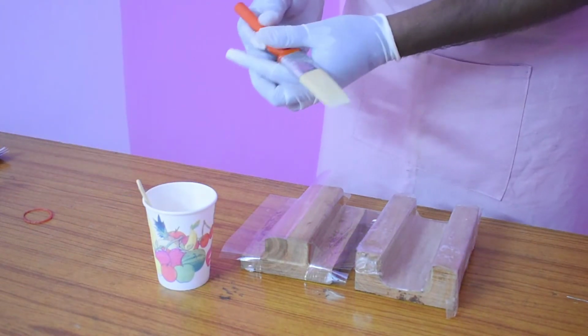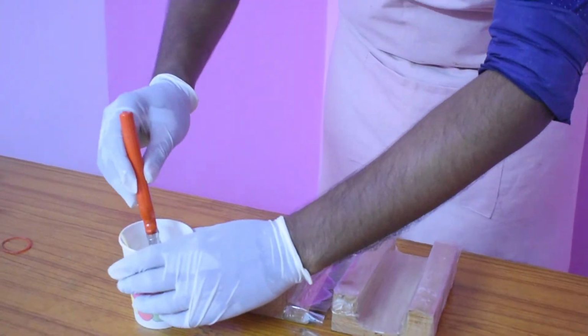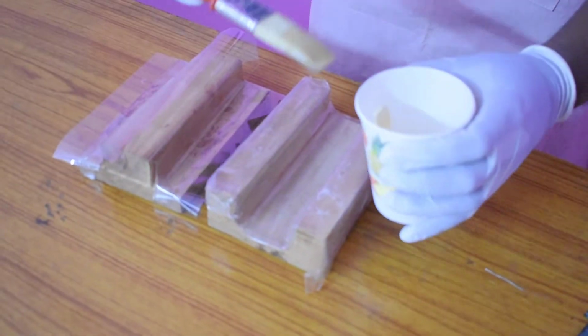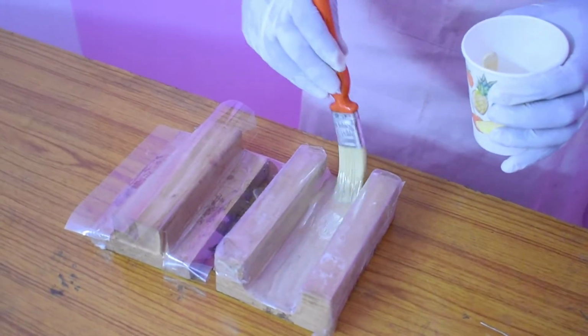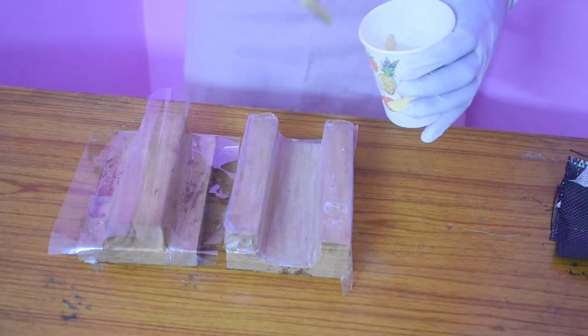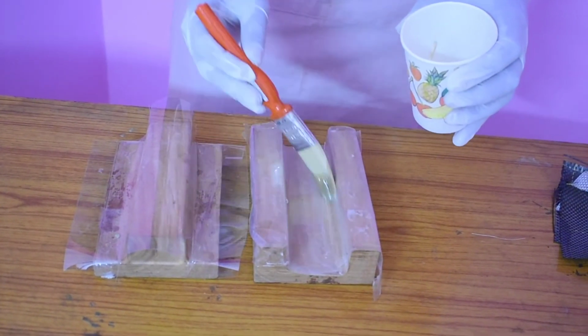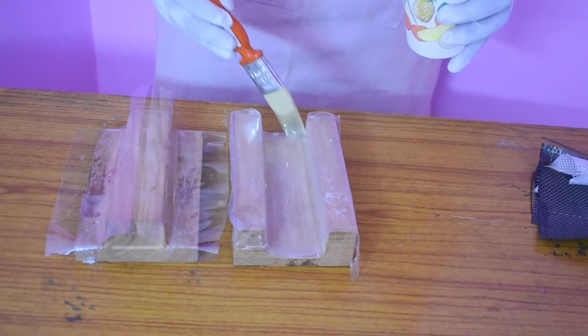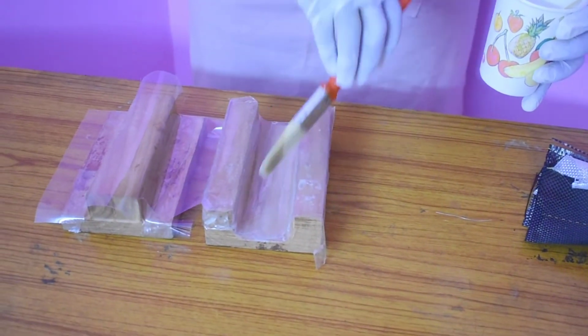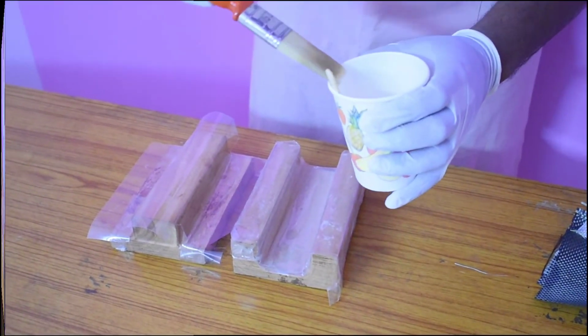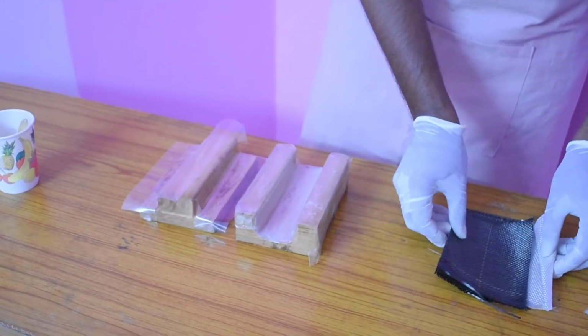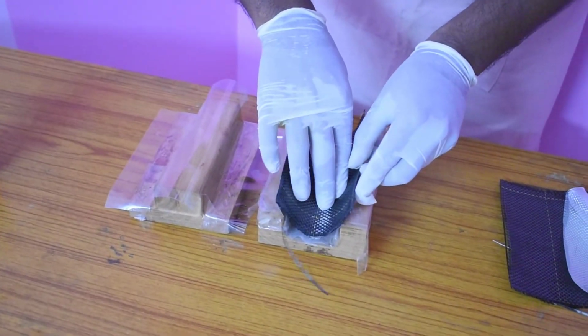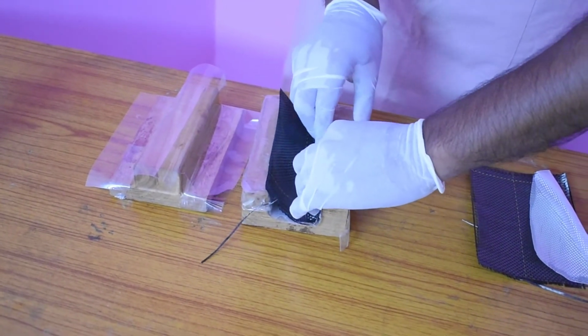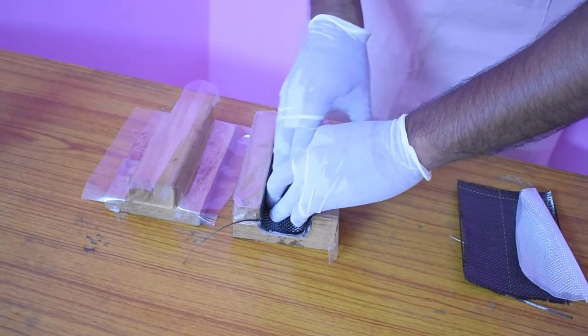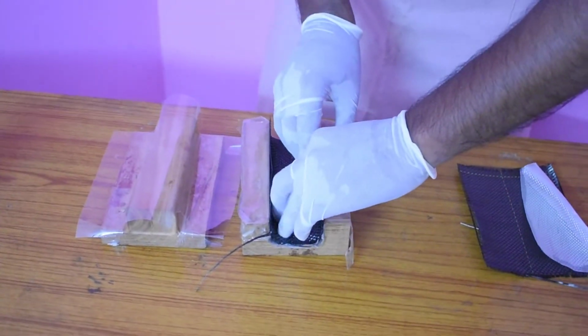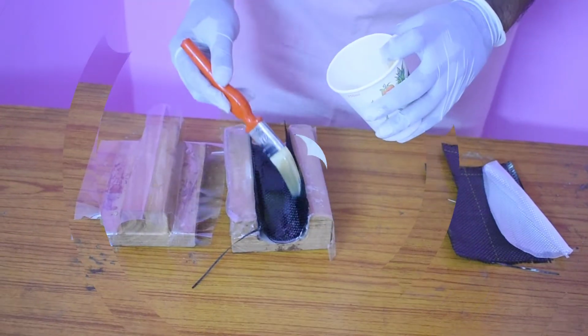Now we are going to apply the first layer coating. So we have to apply the resin in the midsection and the sides of the mold. Now we have applied the first layer of coating. Now I am going to fix the first layer of carbon fiber. Give even pressure so that the finishing will be nice. I am going to apply the second layer coating of epoxy resin.